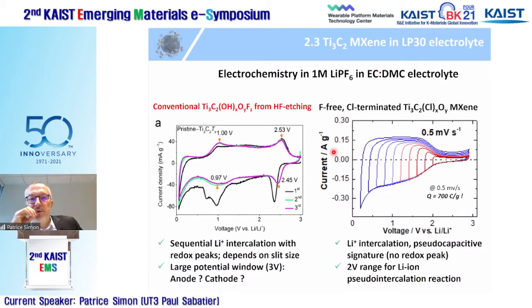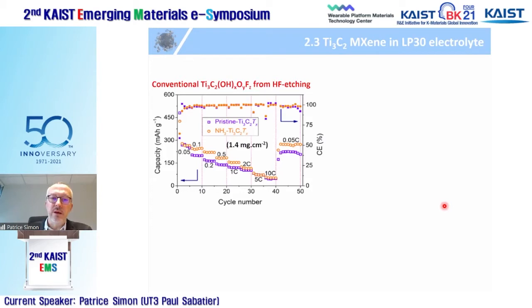The electrochemical signature of our fluorine-free, chlorine- and oxygen-terminated MXene is completely different. So our molten salt MXene shows a lithium intercalation with no redox peak. The voltage range is much narrower, within 2 volts. The mean average voltage is 1.2 volt. And you can see that you have a huge capacity of 700 coulomb per gram. And this unique electrochemical signature, which is symmetric, reminds of the fast capacitive-like signature of a supercapacitor, which means that the lithium ion intercalation is supposed to be very fast. And indeed, this is what we studied next.